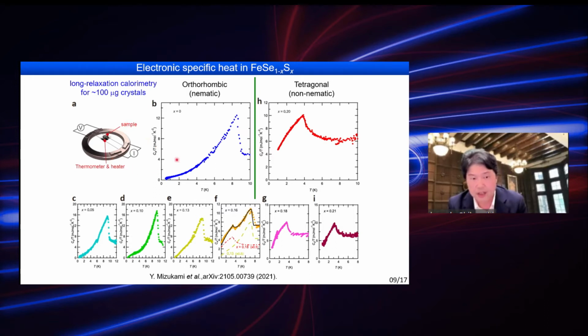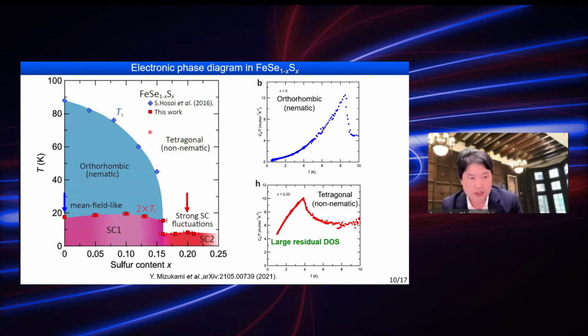We can look at the superconducting transition and low energy excitation by looking at the low temperature C over T. Using this technique, we can map the electronic phase diagram, temperature versus sulfur content. As you can see, this is the nematic transition temperature, and this is the superconducting transition temperature, Tc.